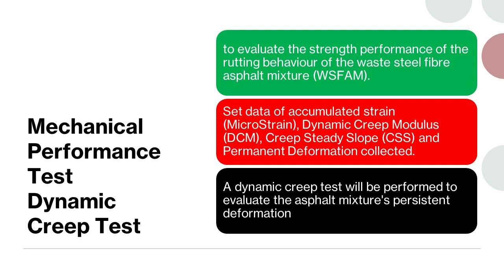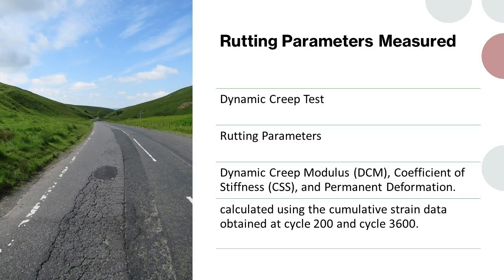The universal testing machine was used to conduct this test. The test will simulate the load of low volume and high volume vehicles with a load of 200 kPa. After conducting the dynamic creep test, several rutting parameters were measured to evaluate the performance of the asphalt mixture. The parameters of interest include the dynamic creep modulus, coefficient of stiffness, and permanent deformation. These parameters are calculated using the cumulative strain data obtained at cycle 200 and cycle 3600.